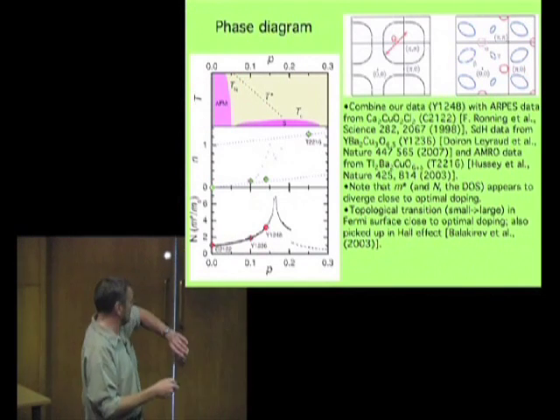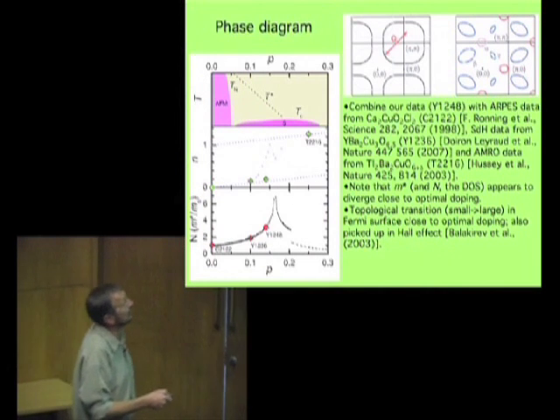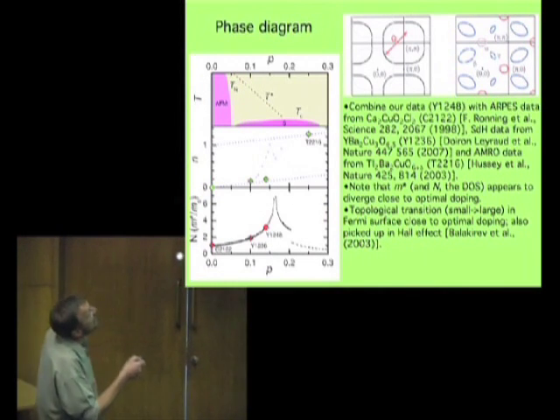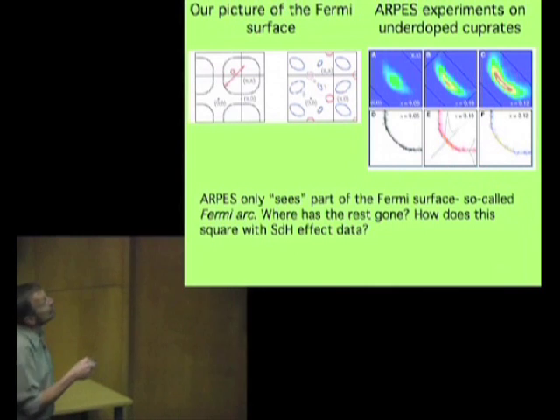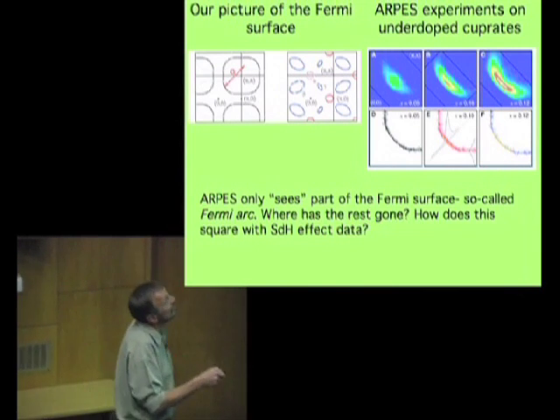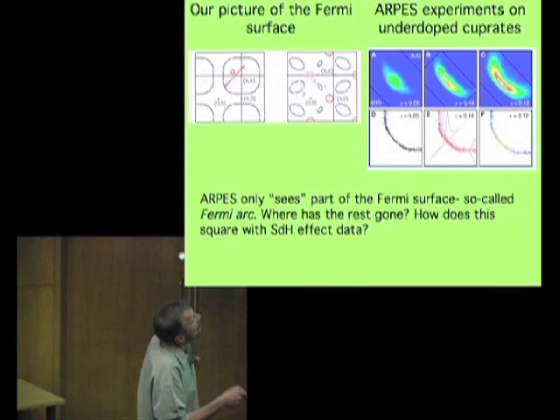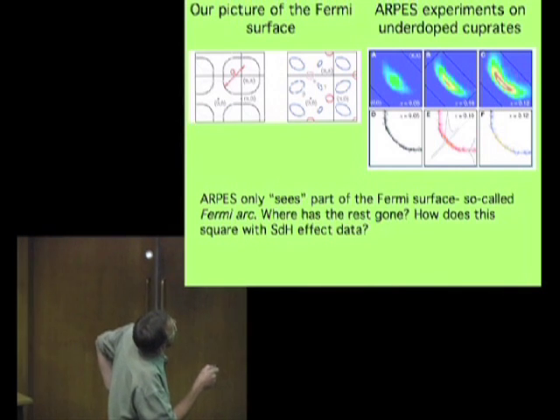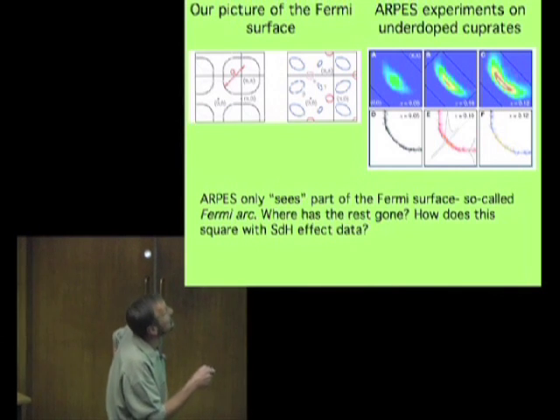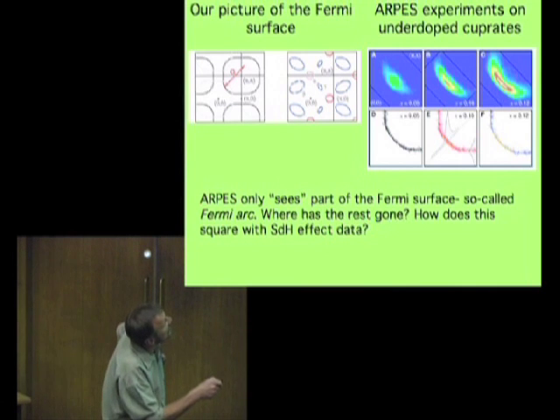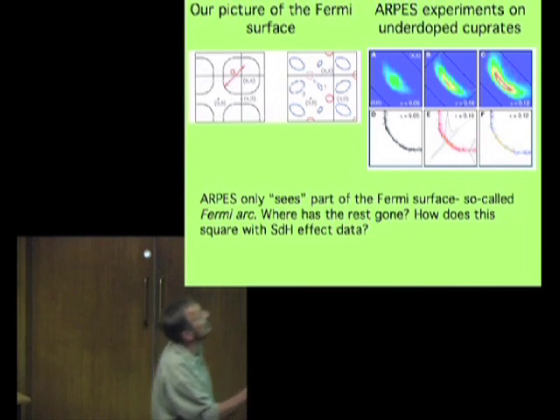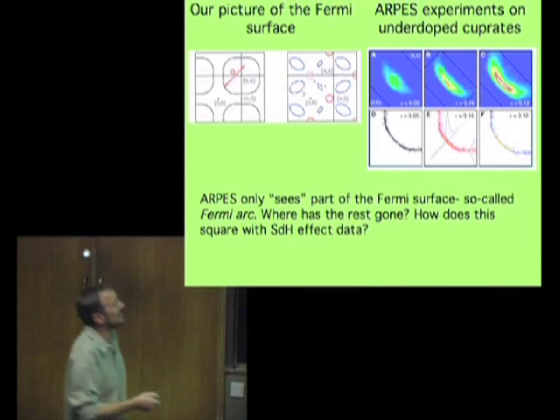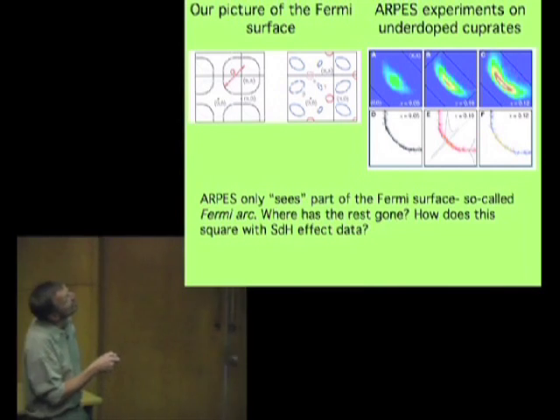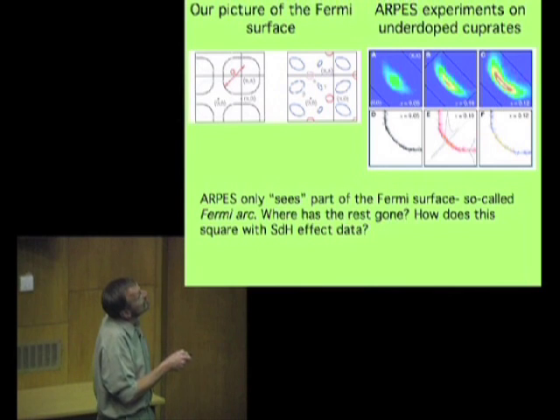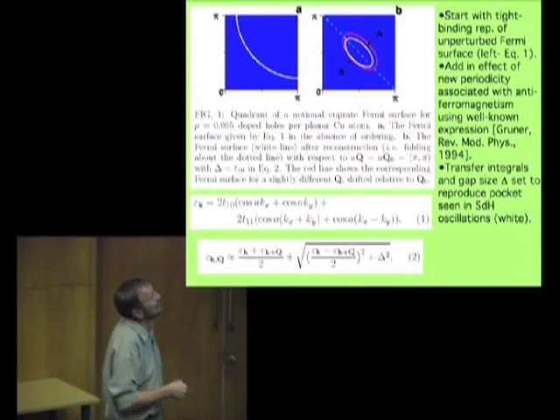So as time is going on, I think I'll just go through these quickly and then go on to this part as to how we can reconcile this picture with the ARPES experiments. You remember that the ARPES experiments were trying to map out this region of the original proposed Fermi surface. They were going along here in K-space, but they were just seeing these brightly coloured blobs like this in K-space. So how does this square with the pocket that's the leftover, this one, from that piece of original Fermi surface?